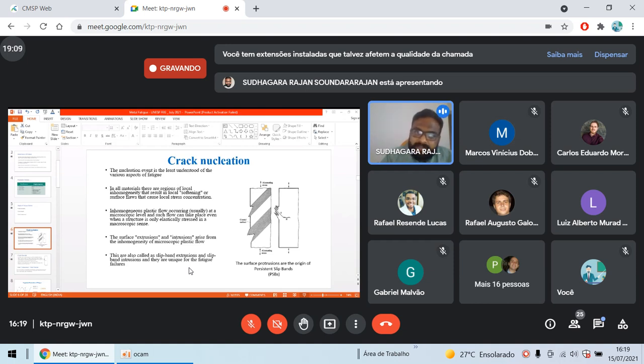In all materials, there are regions of local inhomogeneity that result in local softening, or surface flaws that cause a local stress concentration. That is very important. Inhomogeneous plastic flow occurs at a microscopic level, and such flow can take place even when the structure is elastically stressed. Even when I am stressing the material well below the elastic limit, what exactly happens if the material has an inhomogeneity, a crack, or some third-phase particle in the microstructure? At that area the stress will get enormously increased. That is called stress concentration. That stress will lead to a local plastic flow.